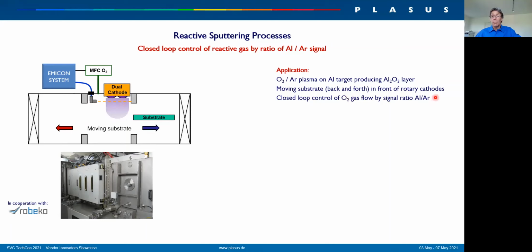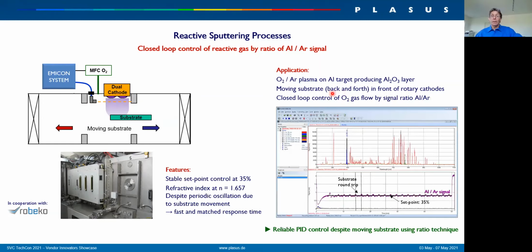So what we set up is a ratio of the aluminum to argon, and it is very important that you make the ratio to keep this process running over a longer time to actually control the gas flow. That is shown here. On the top, you see the spectrum of this process, the aluminum line, argon line, and oxygen line. And below, I have only shown the ratio aluminum to argon. There was a set point of 35%, which gives you a reasonable aluminum oxide layer. And you see everything was stable. You see the fluctuation, which comes from the substrate moving back and forth, but still there was no running out of the work point. The set point was still kept, and you can make a continuous and stable coating on this moving substrate.